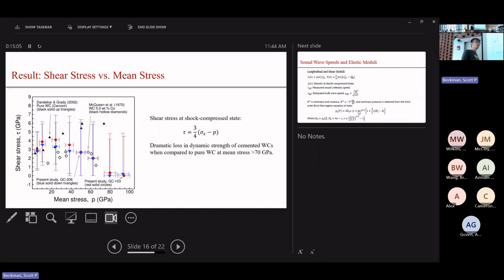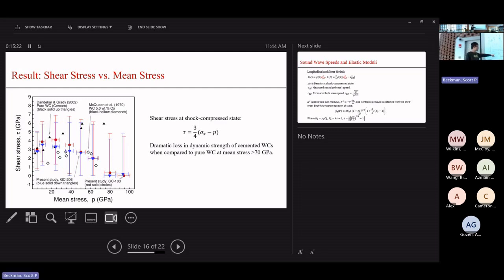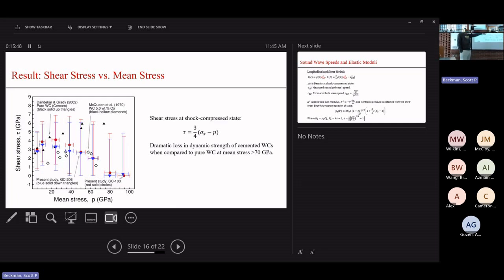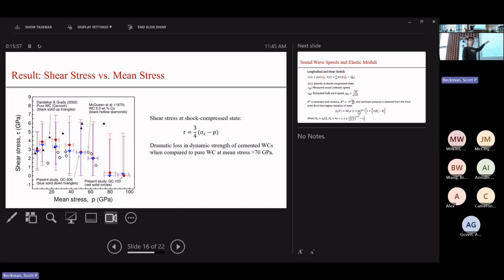This plot emphasizes the shear stress carried by the sample by projecting the previous data onto a shear stress versus mean stress plane. For both grades of cemented tungsten carbide in our study, as well as the cemented tungsten carbide containing 5% cobalt from literature, the shear stress drops to nearly zero when shocked above 80 GPa. On the other hand, pure tungsten carbide — shown as the black diamond — continues to carry shear stress, providing further evidence that pure tungsten carbide retains strength up to that stress level.